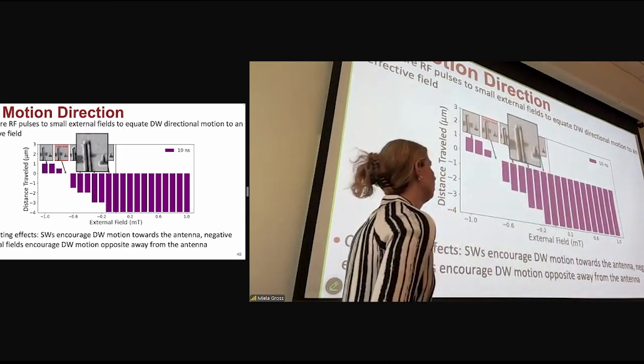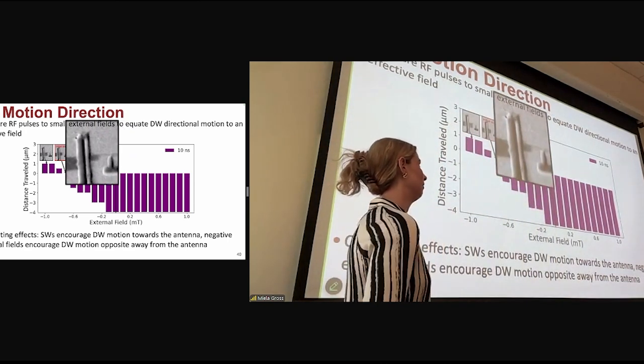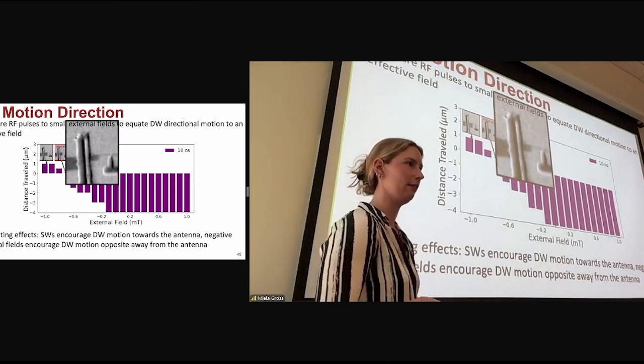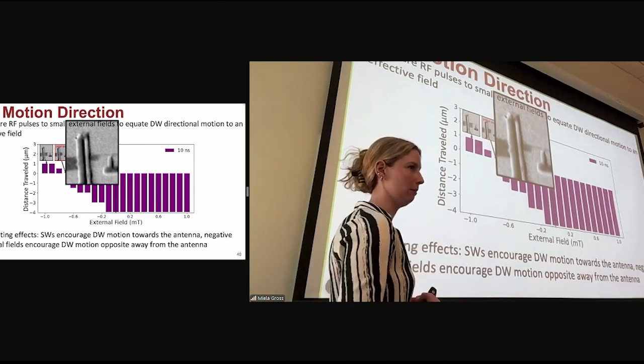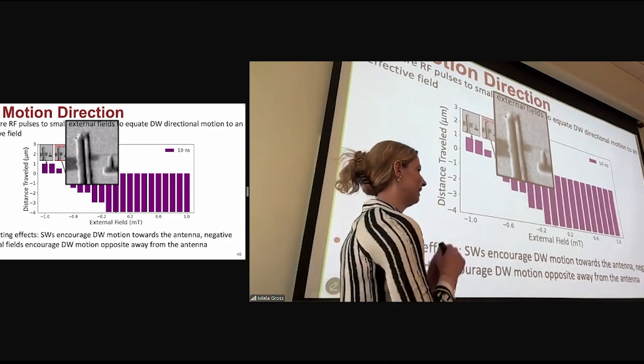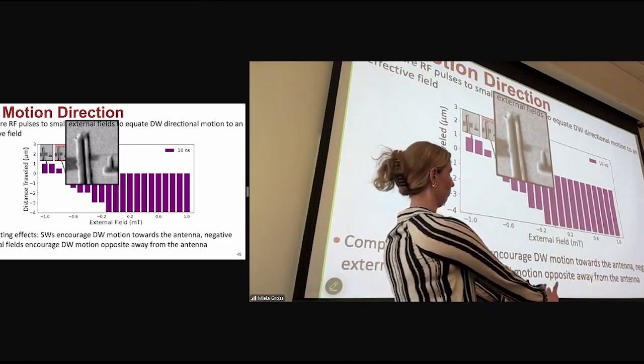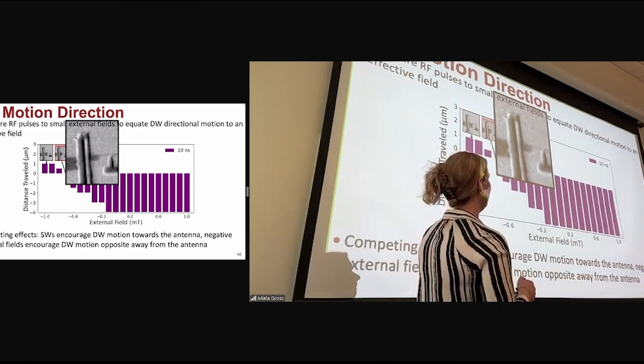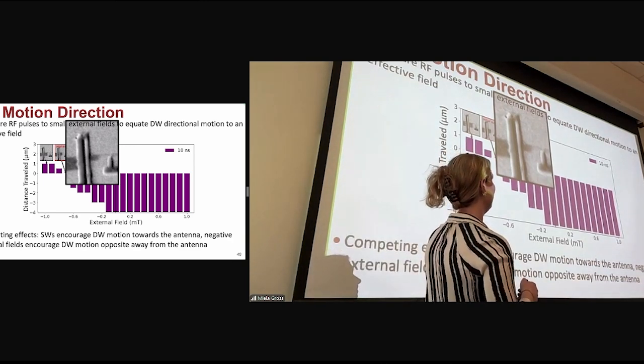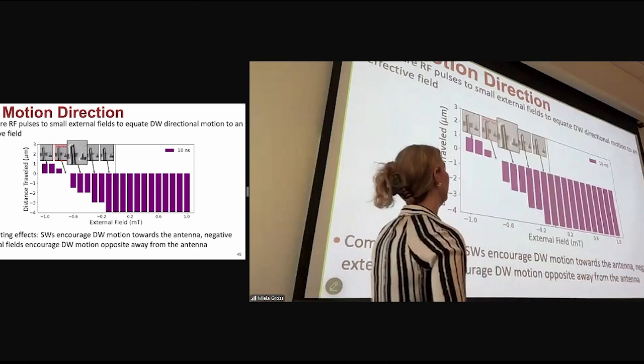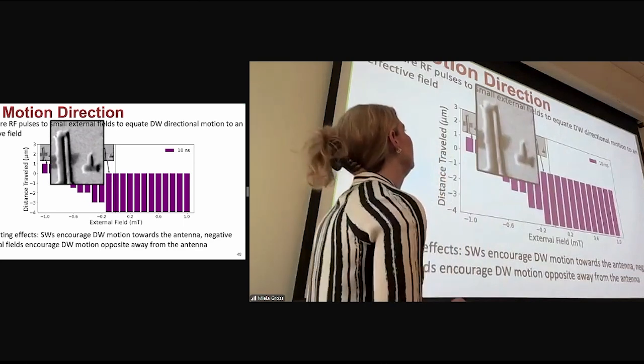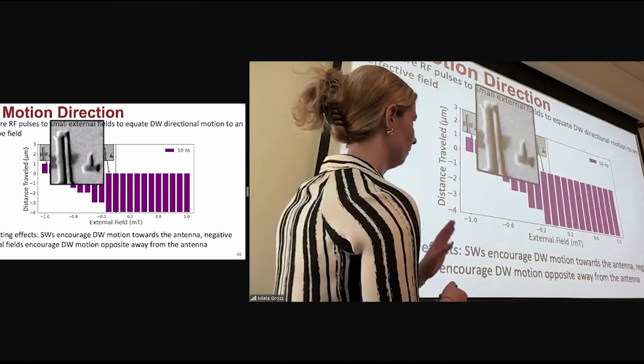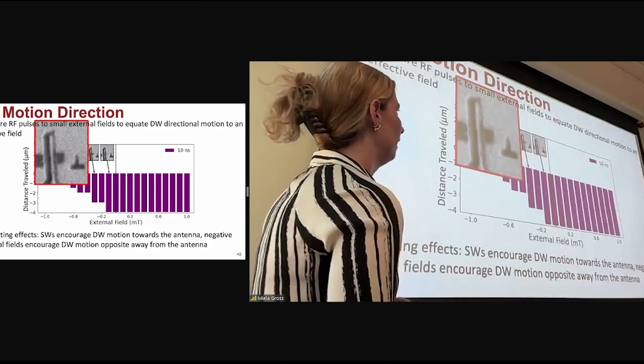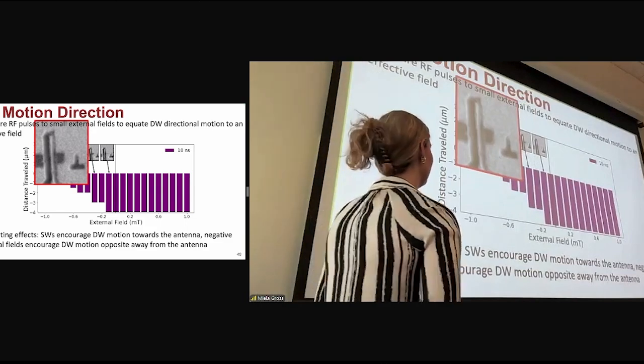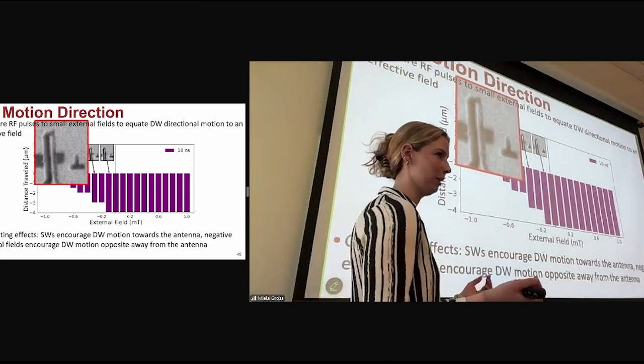But as we start to apply negative magnetic fields, you start to see this competing effect. The spin waves wanting to pull the domain wall left, and the negative magnetic field wanting to push the domain wall to the right. And that causes the domain wall to get pinned just a little bit outside that injector antenna. As we increase the negative fields, that domain wall gets pinned a little bit further and further to the right, until finally we're back at our initial state here when there's no domain wall motion.